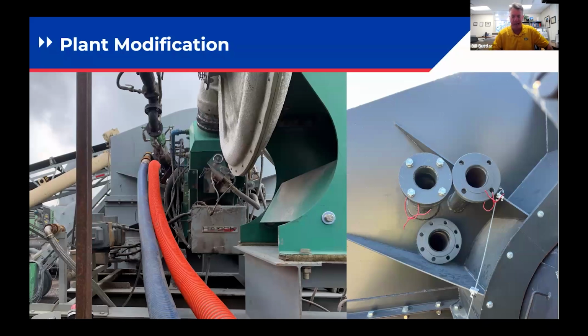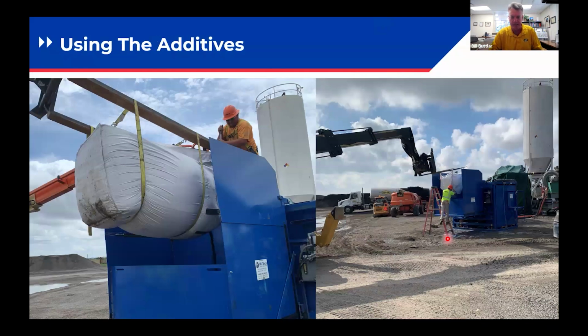Let's see. In terms of the plant, we had to have a 2-feeder system for convenience, so we could do 9 test sections in like 2 days. And so we wanted to be able to switch from feeder to feeder so that we could load one feeder and empty out a feeder while we were starting the next test section. Also, we were using fibers in the SMA, and so we were able to blow fibers and plastics at the same time, or fibers and rubber at the same time. So not too hard to retrofit the plant to do that.